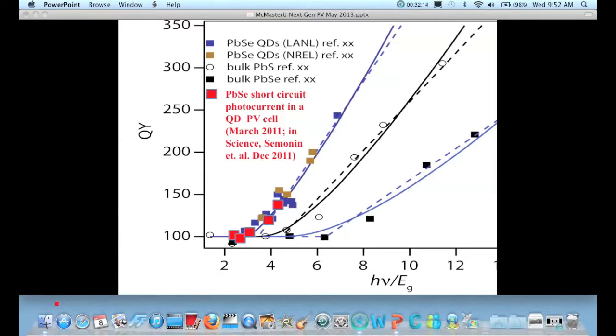And as we'll see in a couple of seconds, when we do the photocurrent experiment, which was reported just about a year and a half ago, that data is quite robust because you count the electrons. It shows the quantum yield, in this simple experiment where you just count how many photons are coming in and how many electrons are coming out, so you don't even correct for reflection, it's the external quantum yield, is greater than 100%.